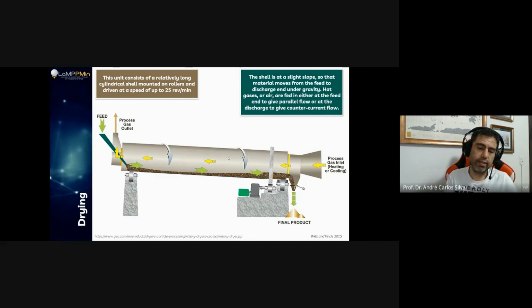Another thing that can happen is if you take this material and put it in a drying oven, for example, when the material comes out of the oven, it's probably going to be blocks or chunks of material, because we're going to have agglomeration because of the temperature. So if you don't want this agglomeration, definitely you have to go to a rotating drum like this. And definitely you're going to lose a lot of material, because we're talking about fine particles, and as these particles lose water while turning around, you're probably going to have a lot of dust. You're going to have to manage this dust, and be extra careful with it.